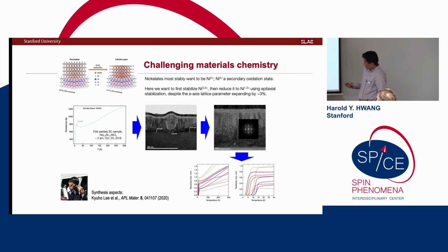It turns out this hint of a partial superconducting transition was a very narrow nanometer or 2 sliver at the interface. And it doesn't reproduce well here, but you can see this looks kind of like a mess, and that's the point. This is all secondary phases, decomposition products, and so forth. Okay. But of course, seeing this taste, we worked hard to try to stabilize this, and we could stabilize a little bit thicker in proximity to this substrate region, this infinite layer phase, and at that point achieve kind of full superconducting transitions in this material.